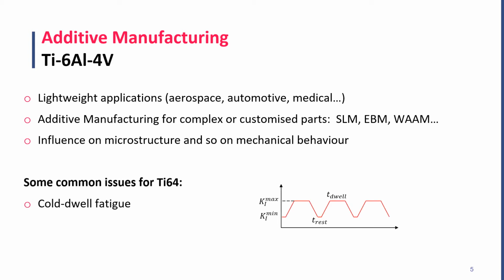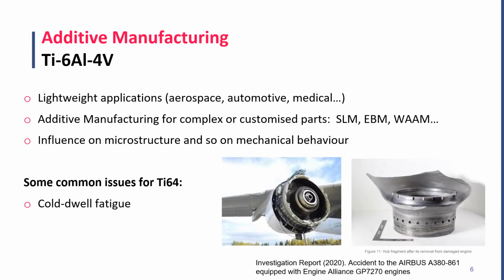Despite the very good properties of titanium-64, creep processes happen even at room temperature. Some failures involving cyclic loading and also sustained loads, as we can see in this loading scheme, have been found, and this is called cold dwell fatigue. Here we can see a failure attributed to cold dwell fatigue of the fan hub that caused the failure of the whole engine of an Airbus aircraft in 2017, requiring an emergency landing.